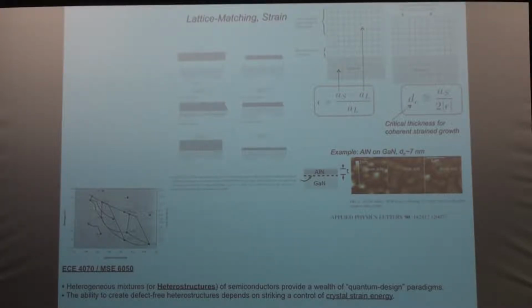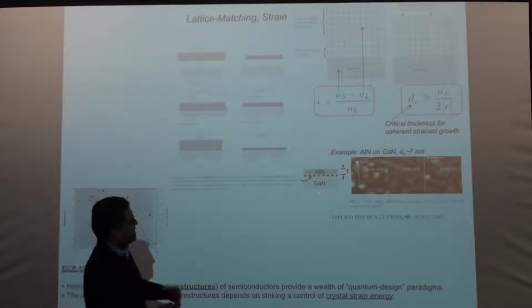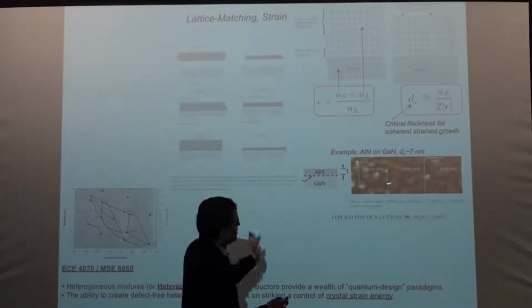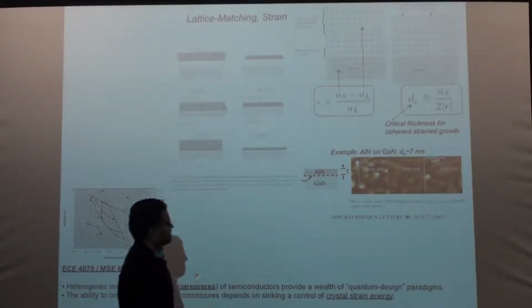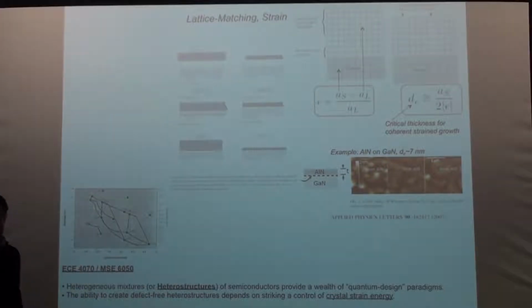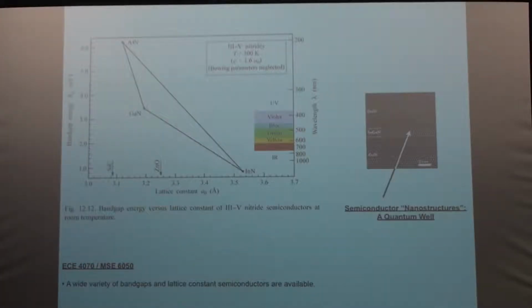So here's an experiment from a lab, for example. I don't know whether you can see. We are trying to grow aluminum nitride on GaN. There's a lattice mismatch, and once we exceed 8 nanometers, you can see cracks and dislocations form and all that sort of thing. But there is a nice window within which you can grow these layers.